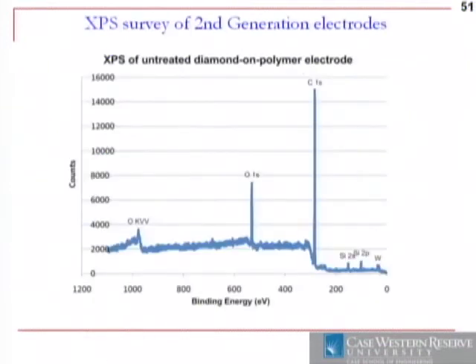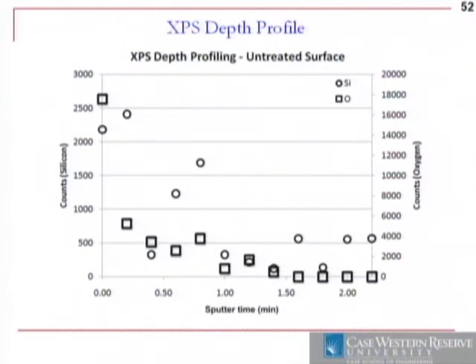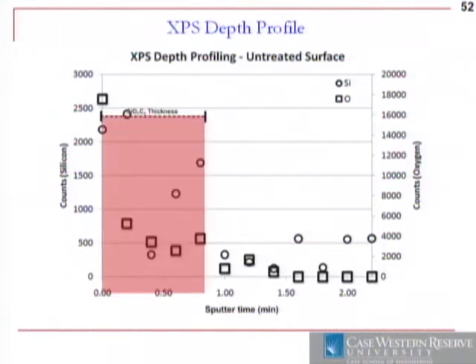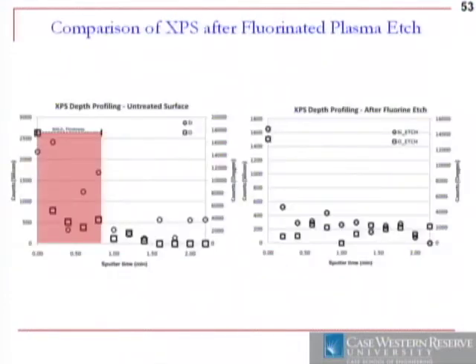To make a long story short, we basically found that there's a silicon oxygen carbon layer on that interface, which is not entirely surprising based on the adhesion of diamond to silicon and how you have to form a carbide. That's reflected here by showing silicon and oxygen, that we can etch through, that there was a layer there. And that's shown there. We've actually etched that away with a fluorine plasma, gotten rid of the layer. There's a slight amount of contamination at the surface.